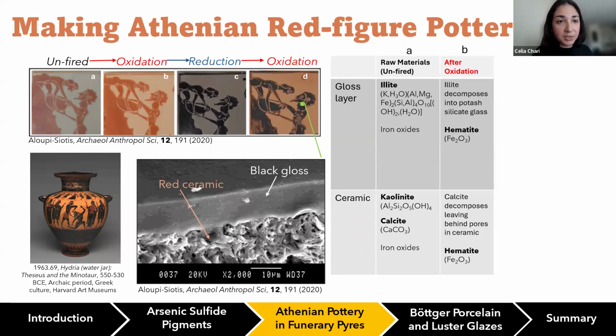In the first oxidation step that you can see here in B, we see that the illite starts to decompose, forming a potash flux. And the iron oxides start to oxidize into hematite. So this becomes really red in color. In the ceramic, we see that the calcite of the substrate starts to decompose, leaving behind pores. And again, those iron oxides oxidize into hematite.